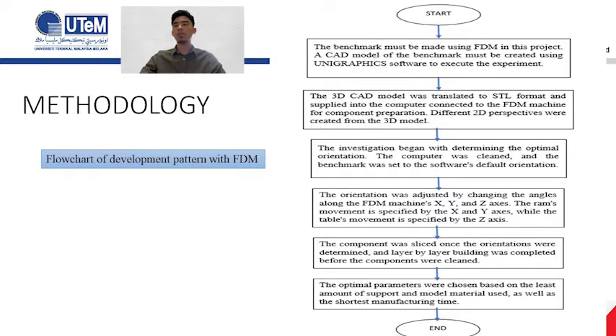And then the component was sliced once the orientation was determined, and layer by layer building was completed before the components were cleaned. And then the optimal parameters were chosen based on the least amount of support and model material used, as well as the shortest manufacturing time.